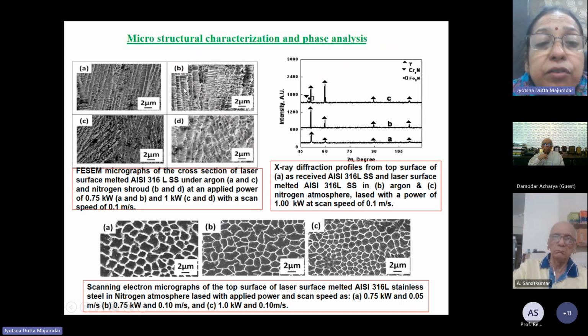So I'll show the results of surface melting of 316L stainless steel. We find that after surface melting, you see a lot of refinement of the microstructure. This is in argon environment, and this is for nitrogen environment. So this is argon environment, and these are nitrogen environment. So we find that in nitrogen environment there is formation of very fine nitrides of Fe2N and also chromium nitride.